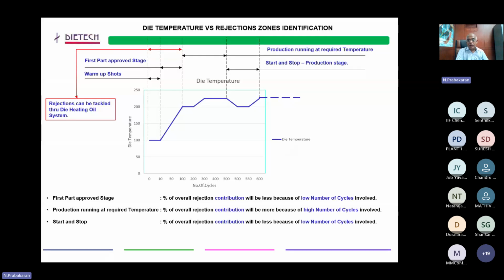From those 50 cycles, I'm assuming that process parameters are settled, and then the casting gives whatever the minimum percentage, 3 to 4% or 5% rejections, is coming. After that, there will be start and stop stages. That's also included in the production stage itself. If your start and stop is a very short time, it will not drop down below 200 degrees centigrade. And then we can take the further cycles to go.